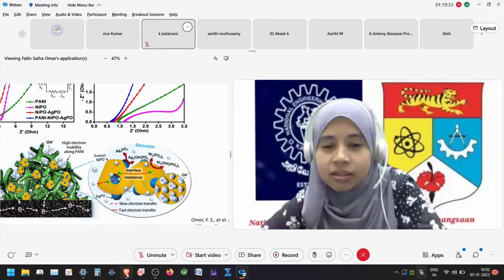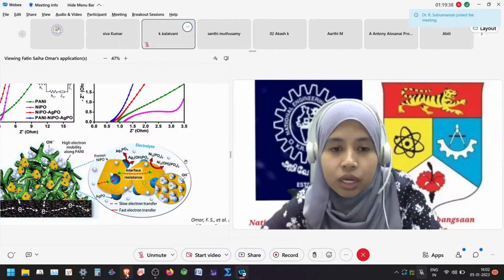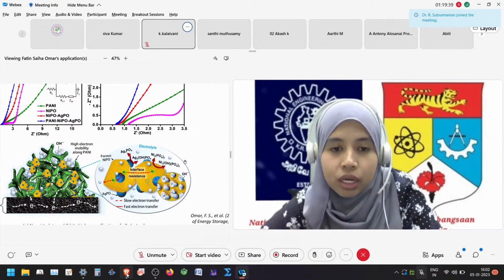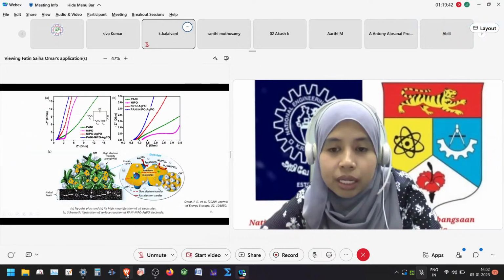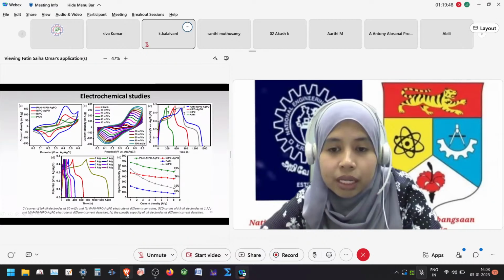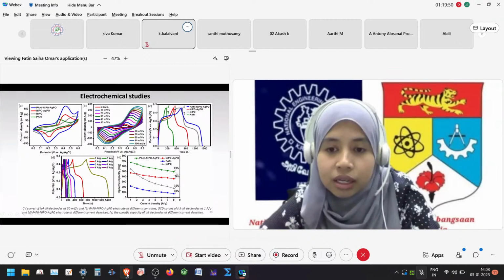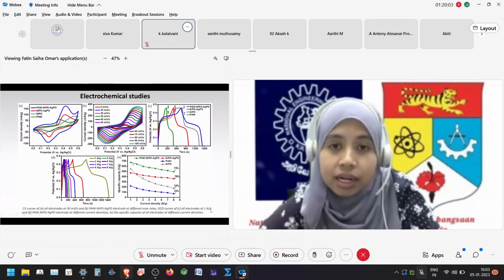Okay? And the green one is polyaniline. It's just used to further enhance the performance. But still, the rate capability of polyaniline nickel phosphate silver phosphate is lower than the nickel phosphate silver phosphate, which has 73% versus 76%. Also, this can strongly support that stability is influenced by the structure, because polyaniline has a semi-crystalline structure.